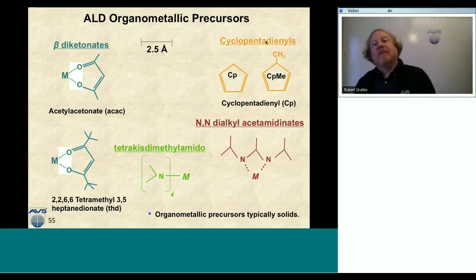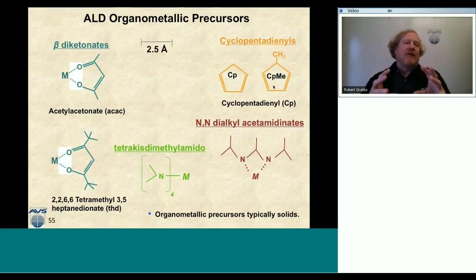The third are these cyclopentadienyls. We have CP, cyclopentadienyl. It's a 5-membered carbon ring with 2 double bonds. And then we've got this methyl cyclopentadienyl as well. The most interesting precursor from this is the platinum precursor, which is trimethyl methylcyclopentadienyl platinum.